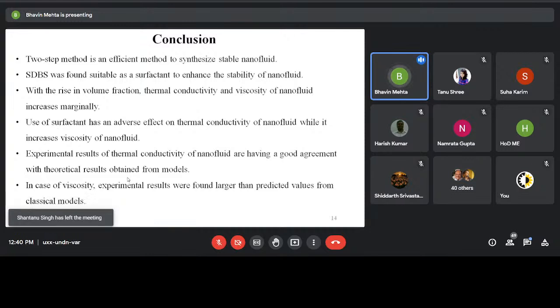So at last we can say that if we want to synthesize the nanofluid below 1% volume fraction, then we can synthesize without the use of surfactant. And that could give you better thermal conductivity compared to using the surfactant. But the role of surfactant will be significant for stability enhancement when the volume fraction is above 1%.